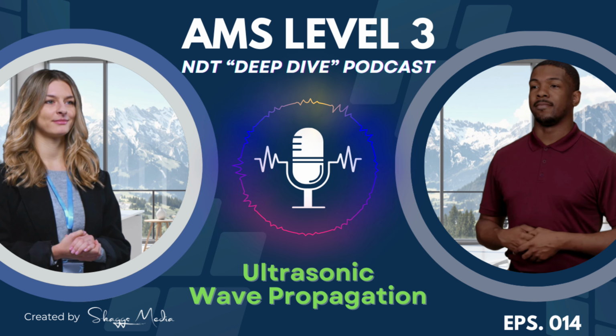Okay, so below the critical angle, when the incident transverse wave hits the boundary, the physics demands that it generates both a reflected longitudinal wave and a reflected transverse wave. You get mode conversion. It has to happen to satisfy the boundary conditions, how the stresses and displacements behave right at the surface. Both L and T waves bounce back.